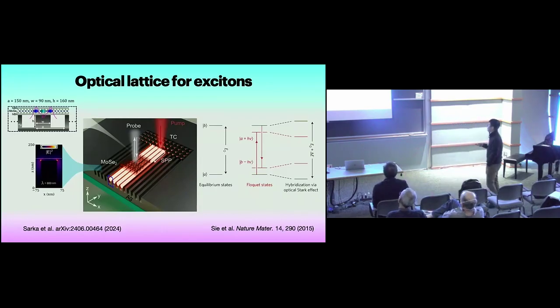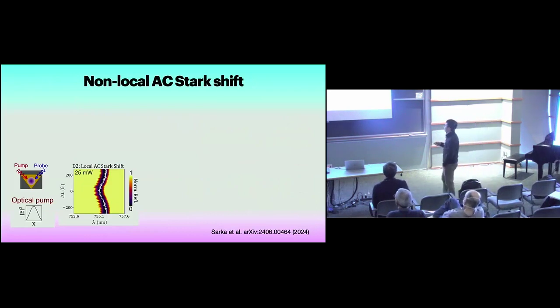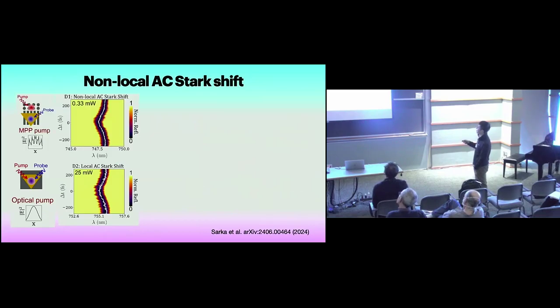Okay. So when we do the experiments, we first compare a free space AC Stark shift by pumping and probing at the same spot. You see that typical AC Stark shift. And then we do the experiment where we pump remotely and launch the surface plasmon polaritons from the incoupler and create some modulation on these TMD layers and probe in the far field. We see a similar shift, but if you look at the power required to induce the similar AC Stark shift, you see that we actually have a drastic reduction in the amount of power that's needed.